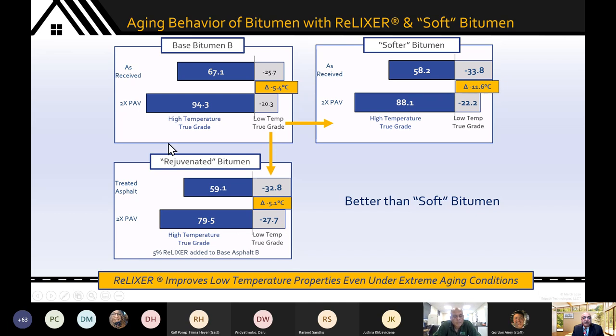And here is a bitumen that was obtained from a refinery. We went through the process and came up with a delta TC of -5.4. We took 1 grade softer from the same refinery and performed the same delta TC measurement and came up with -11. We took this material, rejuvenated it with a bio-based rejuvenator and came up with a pretty similar -5 kind of read. So it does matter. You should ask yourself this question. It does matter how the refiner was able to achieve his softer bitumen. And as you go through your process, you need to be able to ask these kinds of critical questions. What is my input raw material into the process? Remember, like wrap, like aggregate, like virgin bitumen, softer bitumen is also an input material into your process, and you need to characterize it to make sure that it meets your requirements.